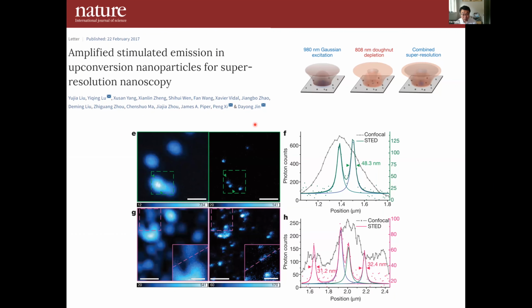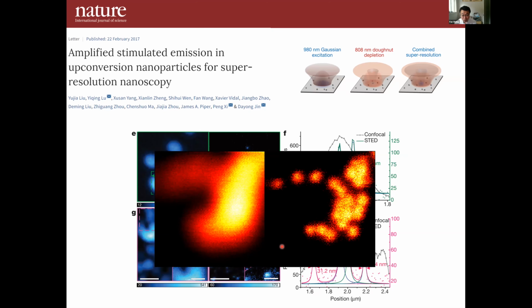So we published this paper. By the way, Xu is over here. Xu is the co-first author of this paper, and we just use the wavelength of 808 nm to match the intermediate level, so we can trigger everything off to turn off the emission, and in the middle we maintain this laser, and then we can achieve really high efficiency. We just need tens of milliwatts of power, and we can achieve a really good resolution. And currently we achieve even better resolution compared with this Nature paper.